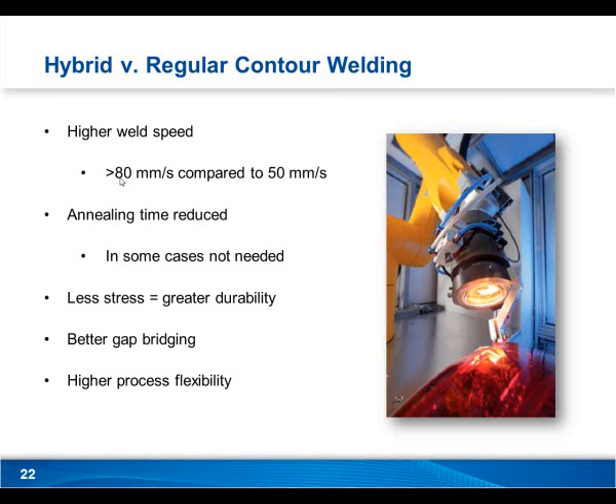So without the halogen radiation, if you turned up the laser energy, then the housing will essentially burn before the lens is going to even melt or have a chance to heat up. But because we're preheating the upper lens, then we can turn the laser power up and travel the laser faster because the lens will already be heated to the point where we can give ourselves more process room, more flexibility with that, and we're not going to burn the housing doing that.